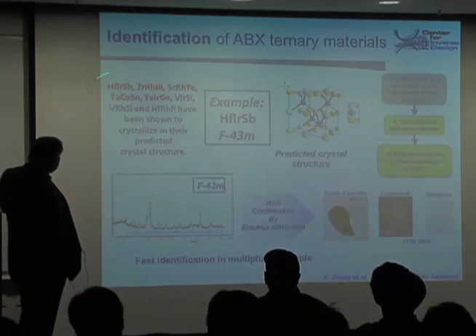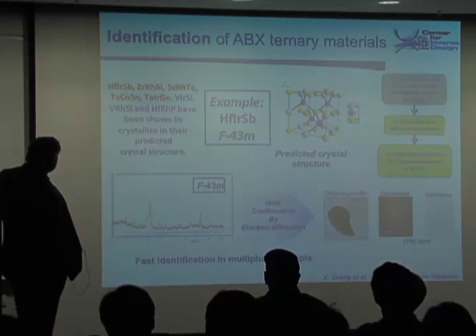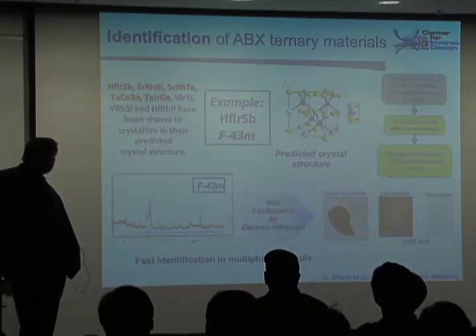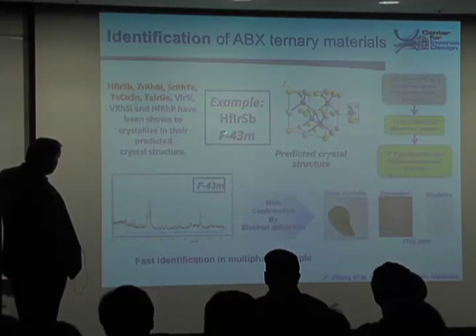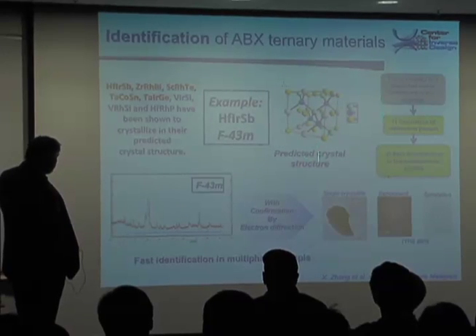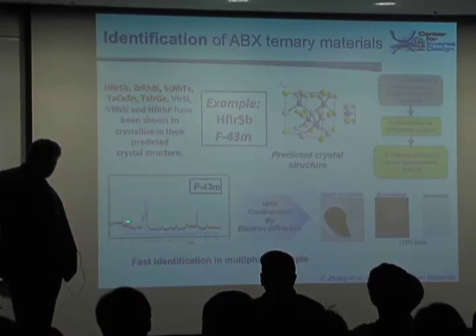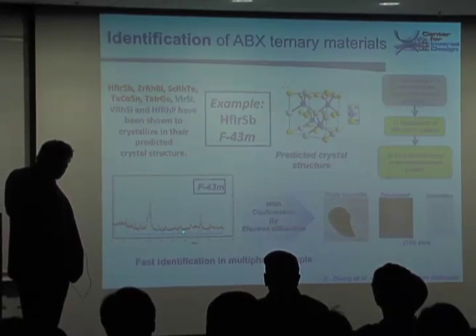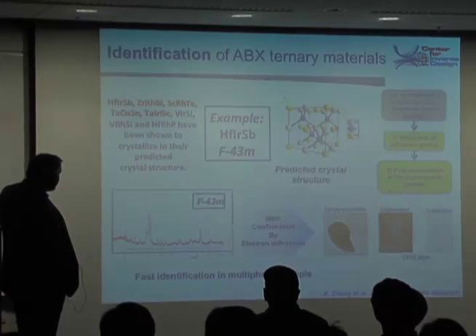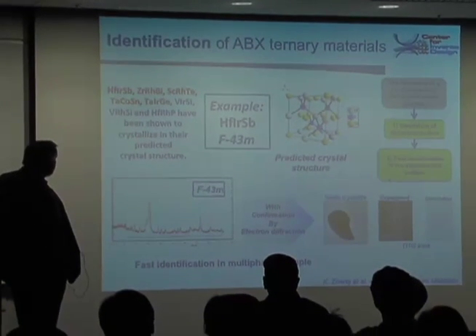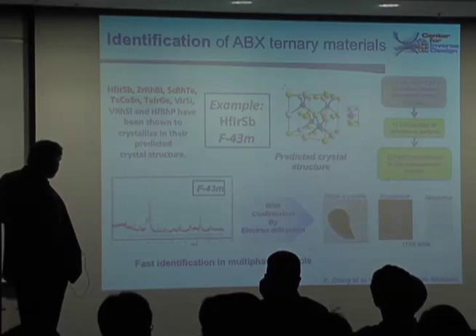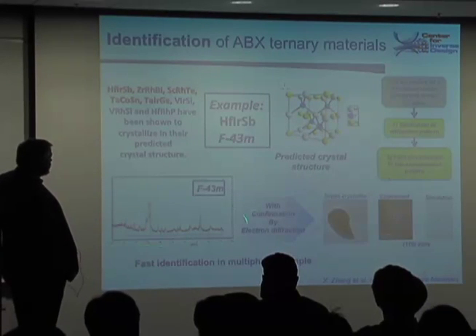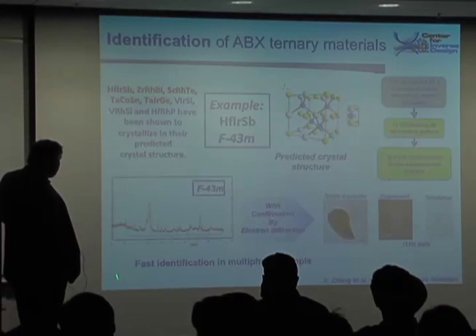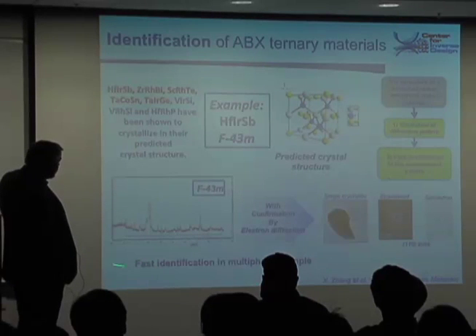And here's an example of this, recently submitted to Nature Materials, with our colleagues at Northwestern and CU. Several of these compounds were predicted to be stable. One of these examples is this system with this crystal structure; we predict this crystal structure, and calculate what that XRD ought to look like. Try to make this system either in bulk or as a thin film, and you can confirm its presence. And so very quickly we can see that some of these are stable.